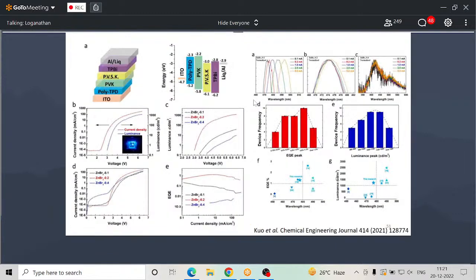And here, this is the device performance. And here we can see the current outputs. If we input current to our system and use some lower-dimensional structures, your efficiency, your light emission won't be stable. You see the EL emission is getting shifted. Whereas with zinc bromide 0.2, if you can tune your crystal structures, you will end up with your 2D structure, which means it is quite stable, and even under high currents it still retains its color quality. So these kinds of systems are quite good and ideal for real-time application. So we did this part.